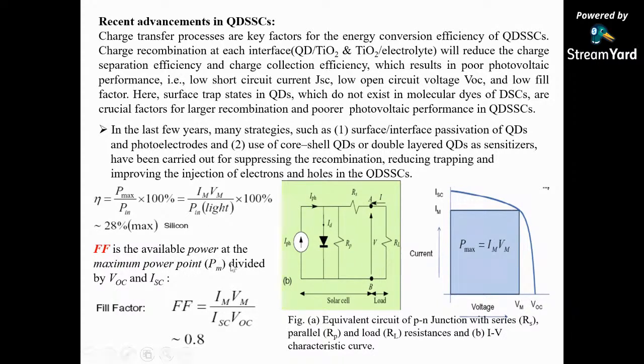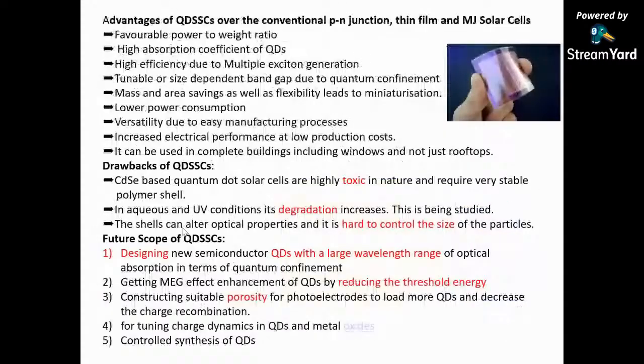So this is divided by the input light power, times 100%. And there is an important factor called the fill factor, to assess the quality of a particular quantum dot solar cell. That is, this P maximum is divided by the short circuit current and the open circuit voltage. So if it is around 0.8, you can get a good efficiency solar cell.